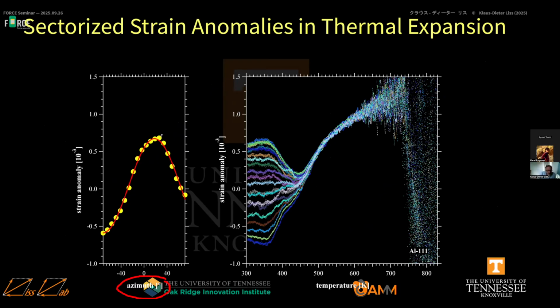And now for each of the points, I can go over here and plot a line as a function of temperature and see how that evolves as a function of temperature. So I see a collapse, the beginning of collapsing of the strain amplitude. Then here it collapses to one line. This is the area of the precipitation of the first phase. Here we have the dissolution of the second phase, and then it changes slope.